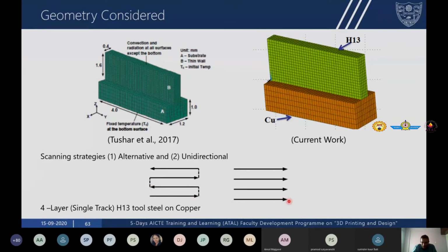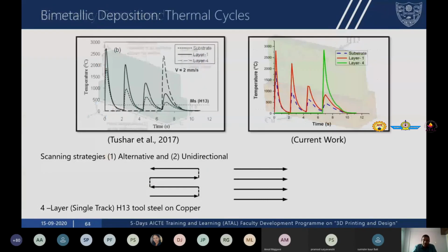You go from left to right, you have a dwell time of a few seconds for the laser to move back to the left, and then again you scan it. This is the alternate scanning strategy, where you go from left to right and then from right to left, and then again left to right, right to left. Now, these are the results published in literature. This is for the temperature in layer 1, layer 4 is the dashed line, and the substrate is the small dashed line. These are our results.